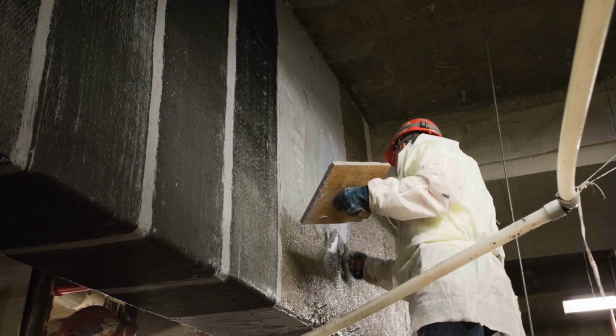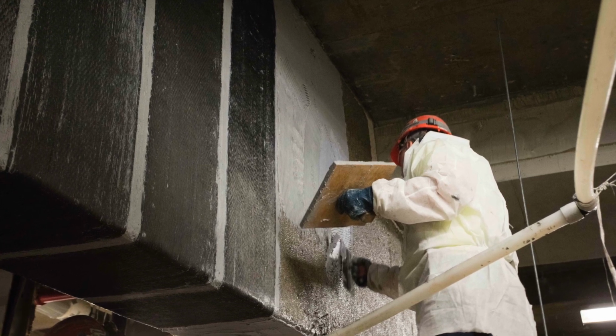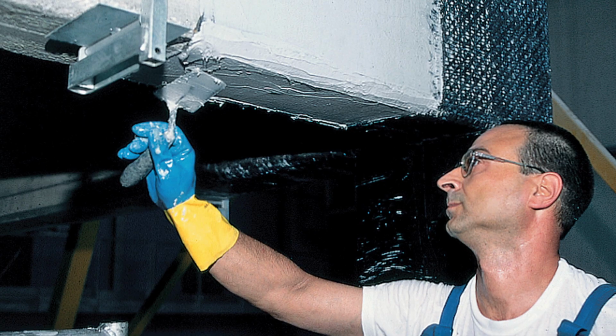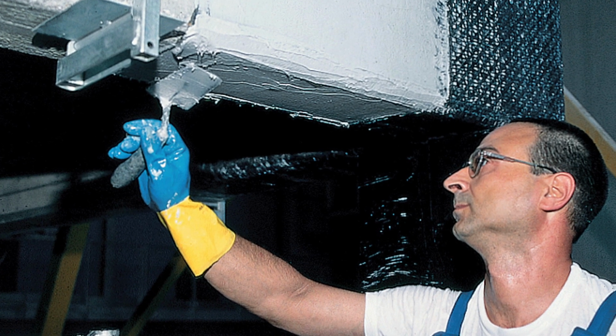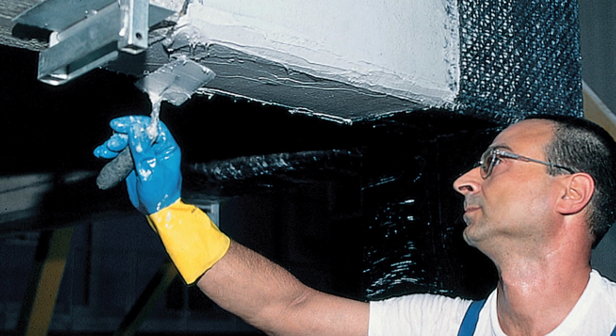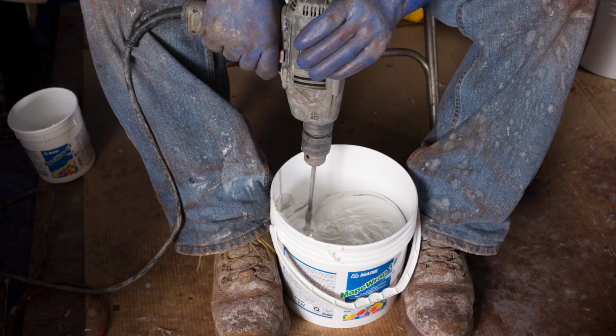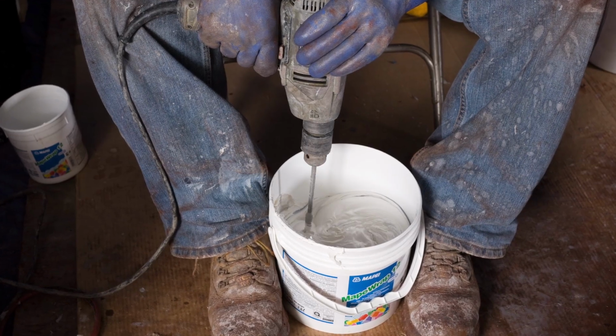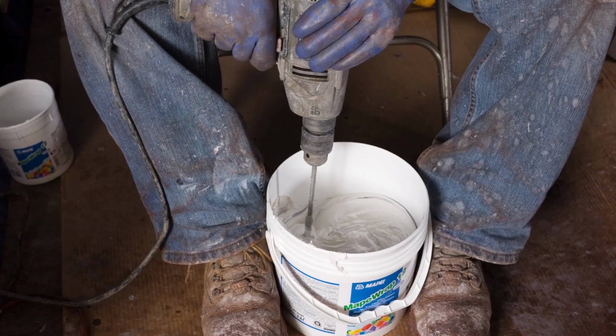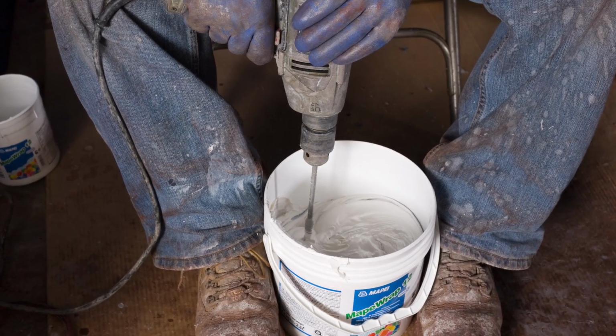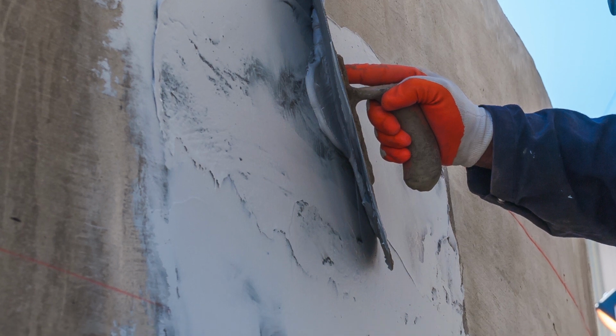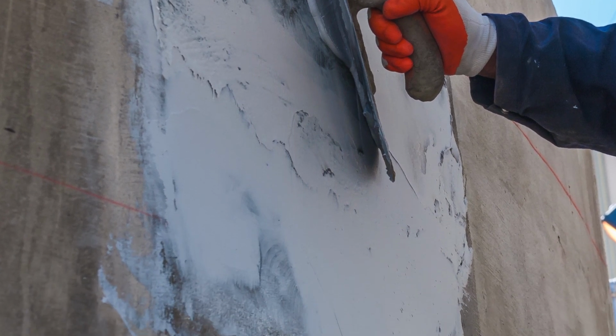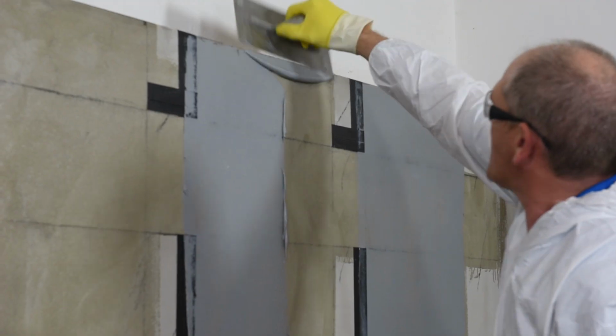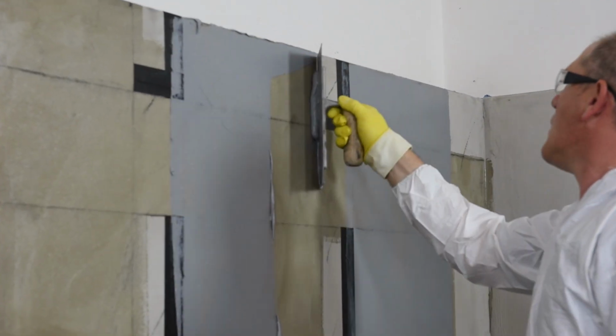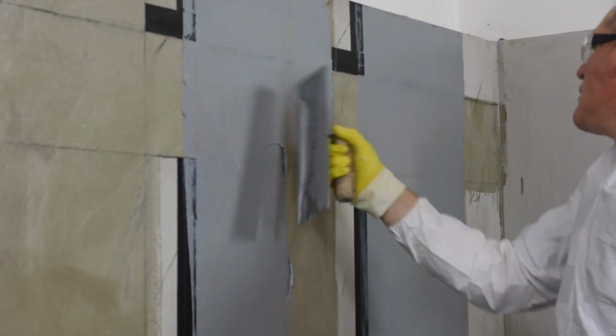MapeWrap 11 is primarily used in cooler climates from 41 to 73 degrees Fahrenheit or 5 to 23 degrees Celsius. It has an approximate working time of 40 minutes at 73 degrees Fahrenheit or 23 degrees Celsius. MapeWrap 12 will provide a longer pot life and is also suited to temperatures from 73 to 86 degrees Fahrenheit or 23 to 30 degrees Celsius. It has an approximate working time of 60 minutes at 73 degrees Fahrenheit or 23 degrees Celsius.